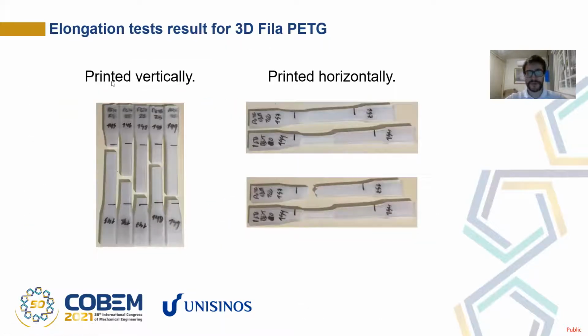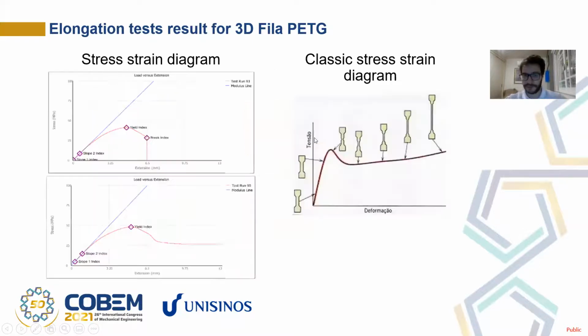So the ones printed vertically broke in the layer lines, same as the other materials, but the one printed horizontally, with the cooling fan turned off, formed the neck and it was spreading through the print until it reached the limit of the test machine. And the one printed horizontally with the fan on, you can see that it formed the neck, and when it would start to spread, it ruptured. Here we can see the elongation test results for the stress strain diagram.